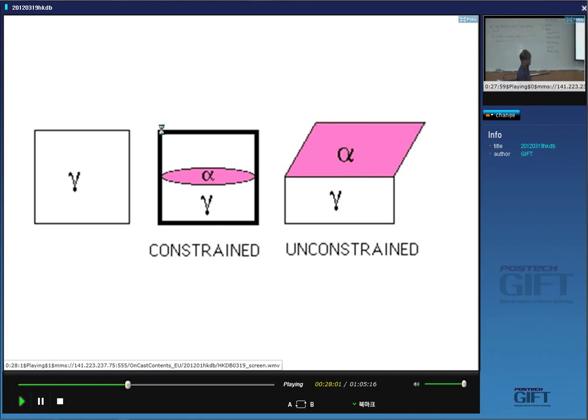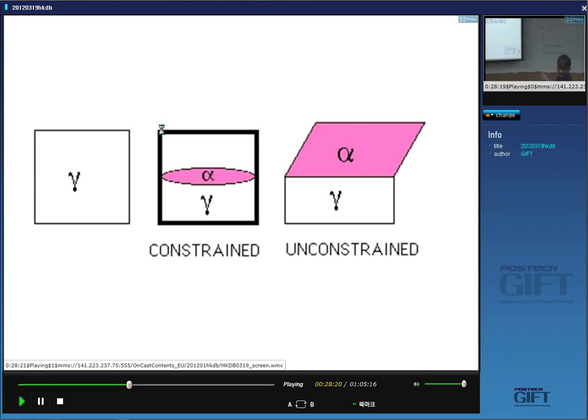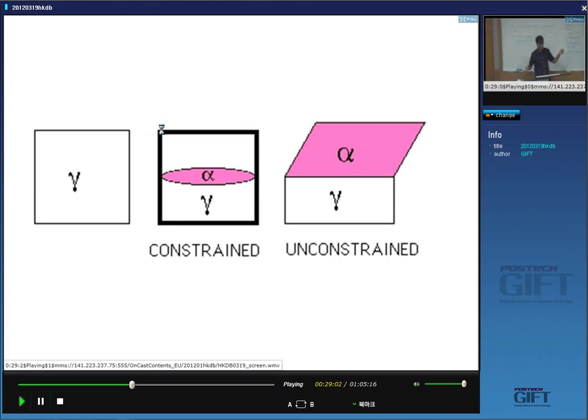This is unconstrained — there's nothing to restrict the change in shape. This is a single crystal in air. But in the vast majority of cases we are dealing with polycrystalline samples, where surrounding grains of austenite push against this deformation. To minimize the strain energy, it adopts the shape of a thin plate. This is what we call the habit plane of martensite — the plane on which the martensite forms.